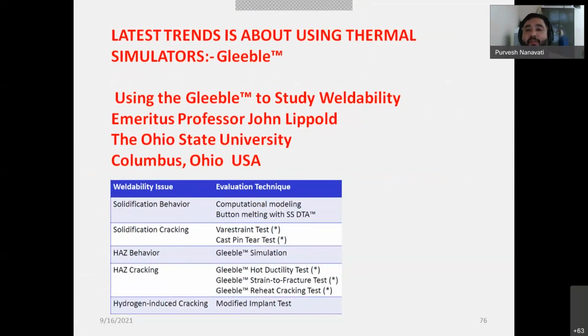Nowadays, thermal simulators are available. So the Gleeble thermal simulator is a very state-of-the-art technology to assess the weldability of the material, and most of the investigations were contributed by Emeritus Professor John Lippold from Ohio State University, Columbus, USA. Using this test, you can assess the solidification behavior and cracking behavior in the weld metal and in the heat affected zone using the Gleeble simulators. There are different simulator versions able to assess the tests, such as hot ductility test, strain to fracture test, reheat crack test, and all this, right?